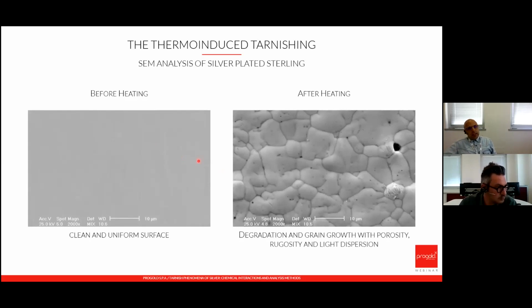Interestingly, the silver-plated sterling, after thermo-oxidation at 700 Celsius, showed heavy damage of the silver coating with the formation of porosity, grain coarsening, and roughness increase that led to light dispersion and reduced reflectivity, if compared with the near flawless situation of the initial sample.